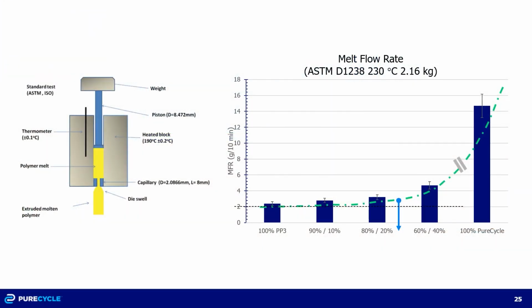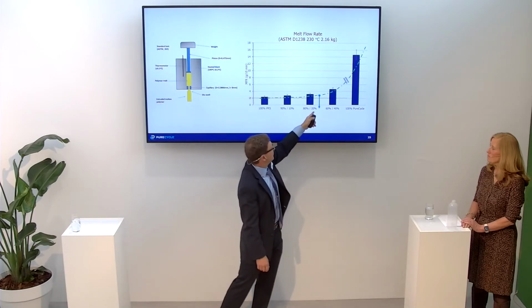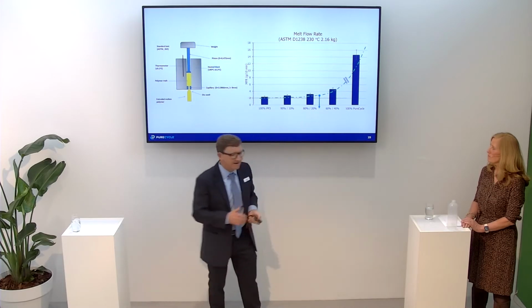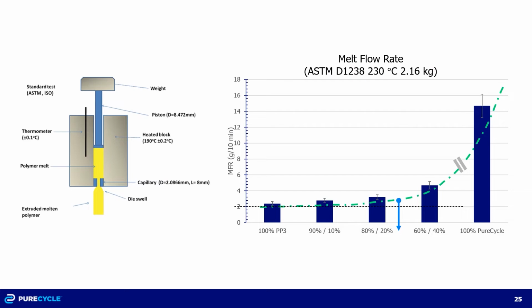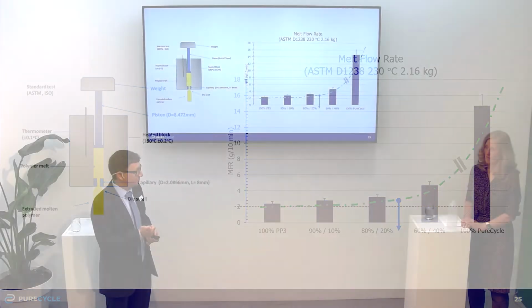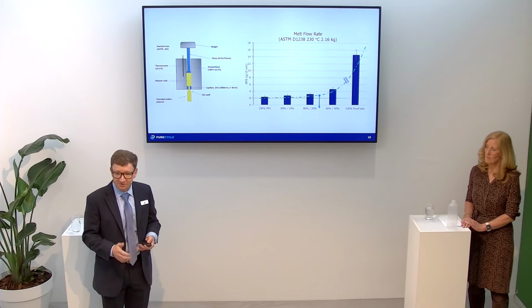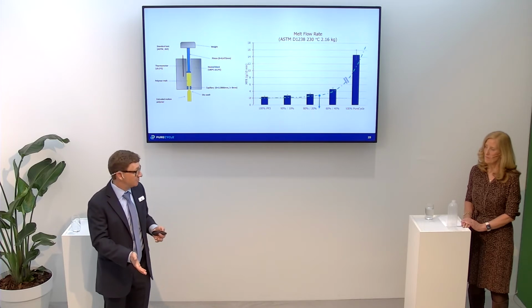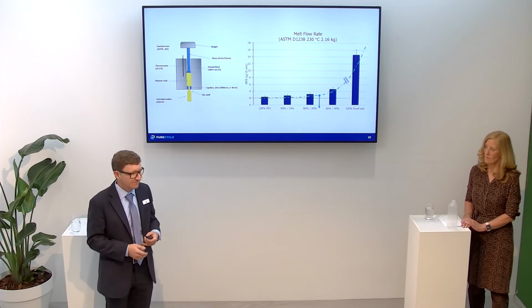If thermoforming or sheet extrusion was the application you were looking for, they took a little over a 2 melt flow homopolymer. Here's the 15 melt flow PureCycle material, and you can see that somewhere between 80-20, probably about 25 or 30%, you're still in the right melt flow range for thermoforming. And that 25% is important, right? Because lots of brands have 25% recycled content commitments. So while we might not be able to get to 100% right now, at least by 2025, and for some of those brand commitments, there's the possibility of blending to get to those mechanical properties.